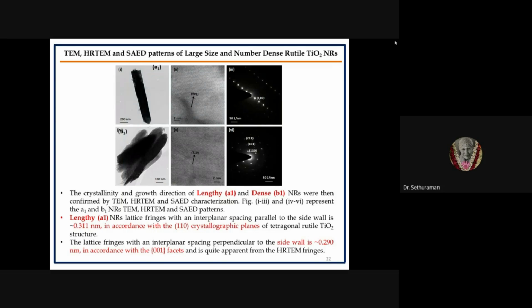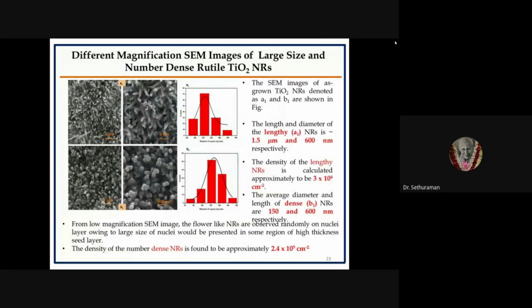Another is for the 001 planes, with an interplanar spacing of about 0.290 nanometer. It's quite apparent from the HRTEM images. So these are lengthy TiO2 nanorods as well as dense nanorods. From the same image, we calculated the length of the nanorods as about 1.5 micrometer, and the diameter is about 600 nanometer.